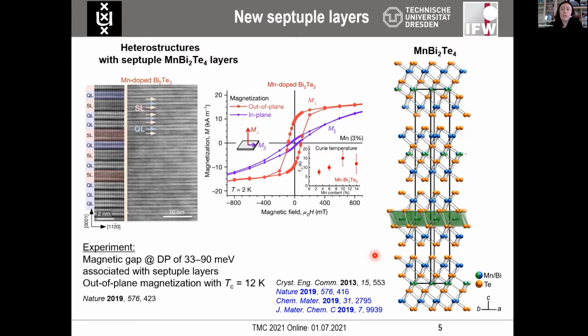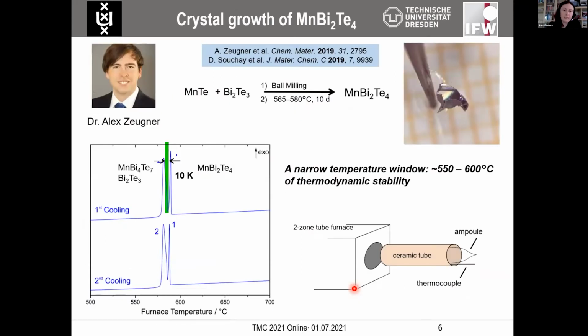So with all this prior information and thanks to the very fruitful exchange with a group of Mikhail and Yevgeny Chulkov, we were very interested to start looking into this material system. And we found indeed that this compound exists, but requires very precise and somehow complex synthetic conditions to be obtained as a single crystal. So it took us some time, several years after the first publication, but then we succeeded and grew this crystal, giving the access to the elucidation of the physical properties. So let me briefly summarize what we have done on the material side, why it was so challenging.